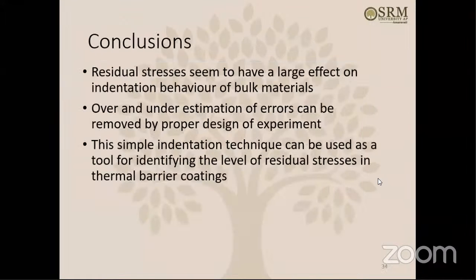So the conclusion of this research is that residual stresses seem to have a large effect on the indentation behavior of bulk material. Over and underestimation of the errors can be removed by a proper design of experiments. And this simple indentation technique can be used as a tool for identifying the level of residual stresses in thermal barrier coatings. Sometimes it causes some very small damage to the surface, but it's insignificant. If you use nano-level indentation, the damage to the surface is very small. So sometimes it is called non-destructive evaluation also, because with a very small indentation you can find out the residual stress in thermal barrier coating. It doesn't damage the material much, and you can immediately find out the residual stress. This is the conclusion of this research.